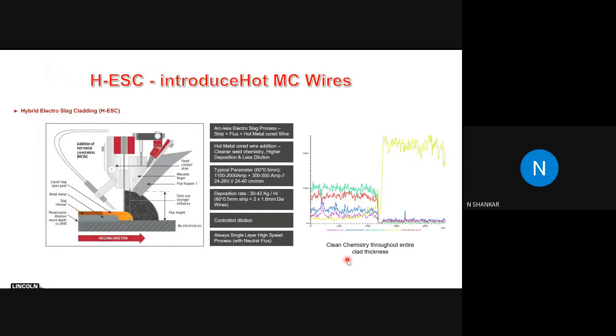Why do I call it a hybrid electroslag strip cladding welding application? I have the same flux being fed on one side, I have the same Joule heating effect, but I introduce an additional metal core wire, maybe one wire, maybe two wires, into the heat zone, into the hot molten material, and the metal core wire takes heat from this, melts and deposits more. So you get a higher deposition for the same current range, and you're going to deposit 30 to 42 kilograms per hour based on your parameter setting.